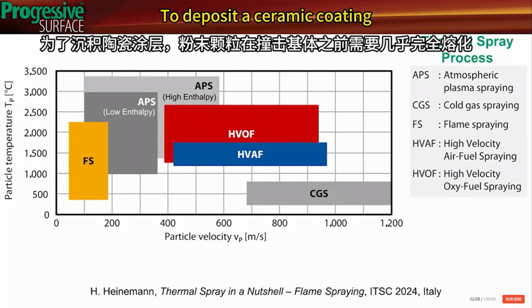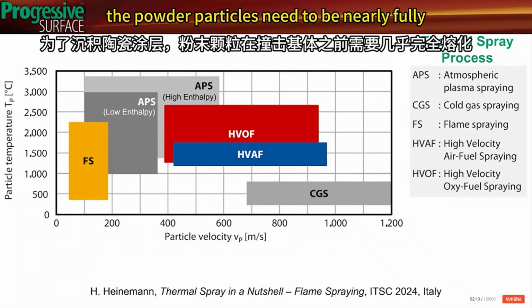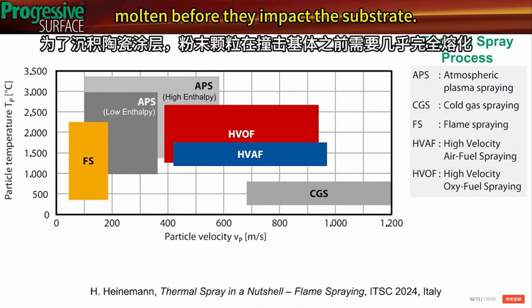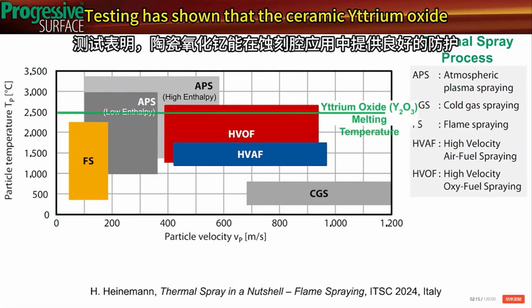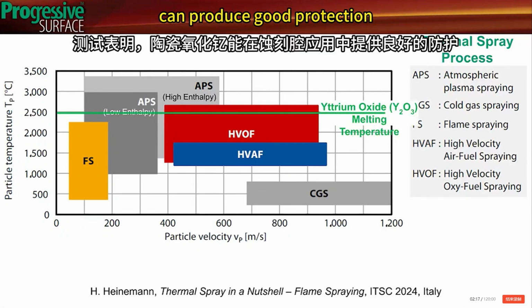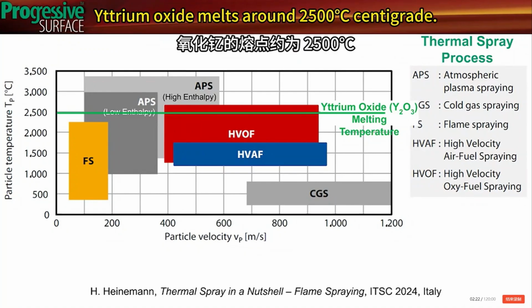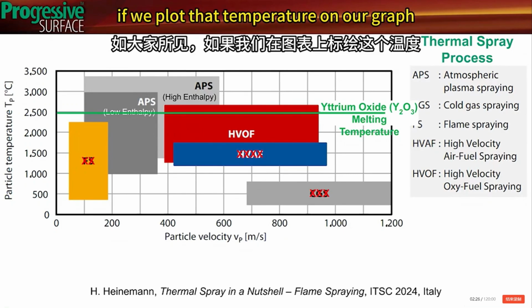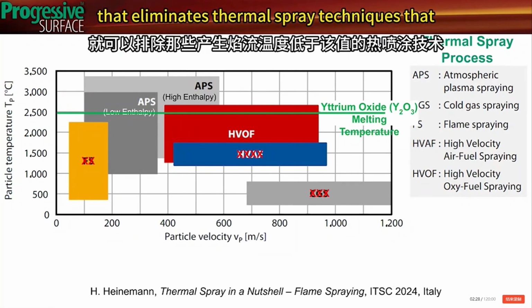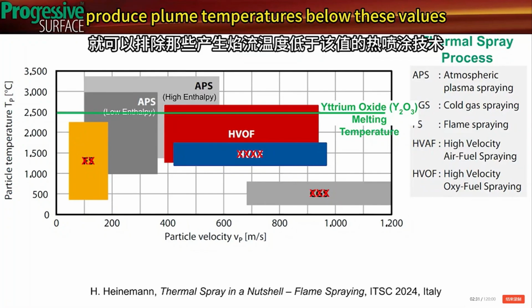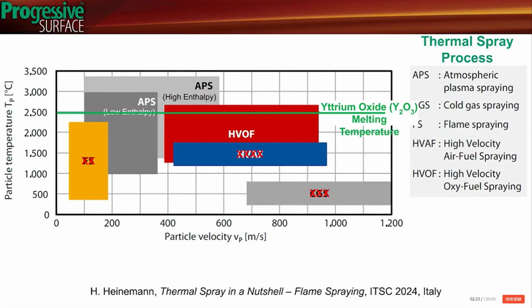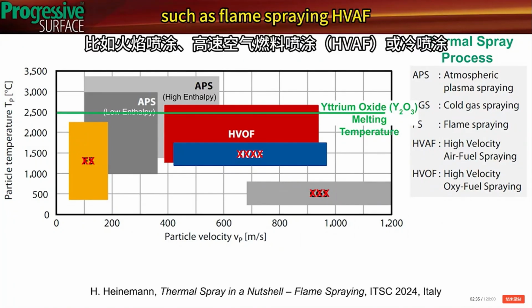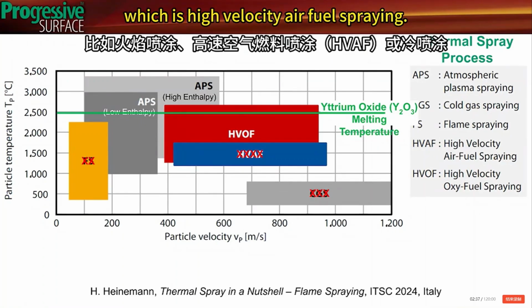To deposit a ceramic coating, the powder particles need to be nearly fully molten before they impact the substrate. Testing has shown that the ceramic yttrium oxide can produce good protection in the etch chamber application. Yttrium oxide melts around 2,500 degrees centigrade. And as you can see, if we plot that temperature on our graph, that eliminates thermal spray techniques that produce plume temperatures below these values, such as flame spraying, HVAF, which is high velocity air fuel spraying, or cold spraying.